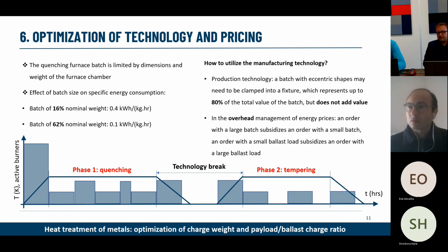Okay, so then we again started digging deeper, and we discovered that in some of the cases, and this is not to criticize the company, it was just the historical way they've done it, up to 80% of the batch weight, and again, the weight equals energy, as you can see on the left-hand side, was ballast, a big jig that basically clamped the value-adding element that was undergoing the heat treatment. So again, one of the exercises and lessons learned was, how do we redesign the jigs so that the 80% of the batch load is not the ballast? And we go back to the manufacturing technology and how we design it.